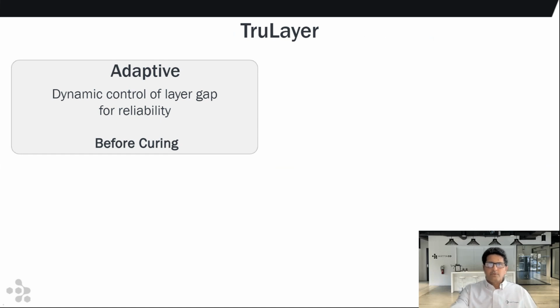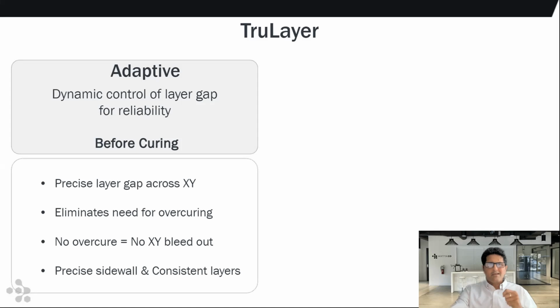So what came into play as we started to tackle this problem was TruLayer technology. And there are two aspects of TruLayer. One, which we call TruLayer Adaptive, comes into play before curing. And another aspect of it comes back after curing. And so how does it truly do it differently? TruLayer Adaptive adjusts the glass that is underneath the layer dynamically before it cures each layer, which means if we need 100 microns, it's exactly 100 microns. And because of that, we never have to overcure the layer because we know that the gap between the previously cured layer and the glass is exactly what's required.